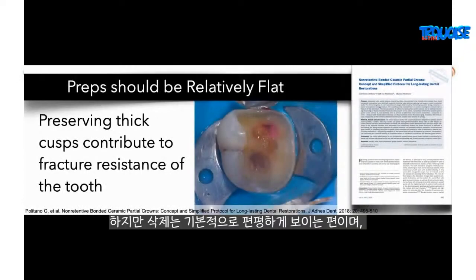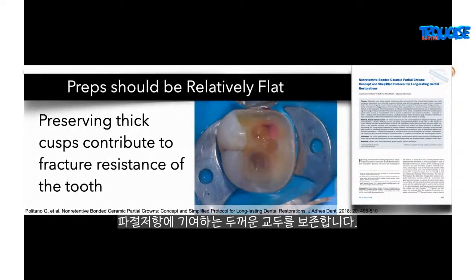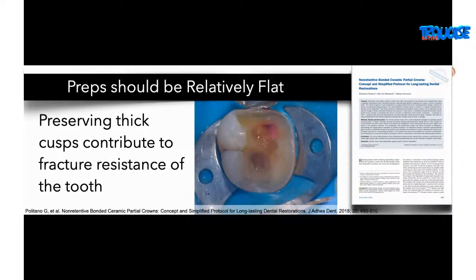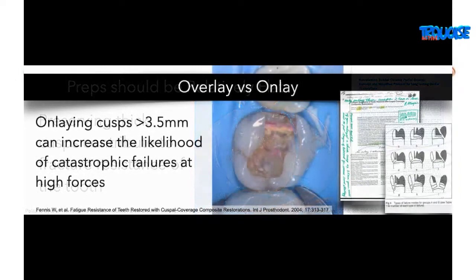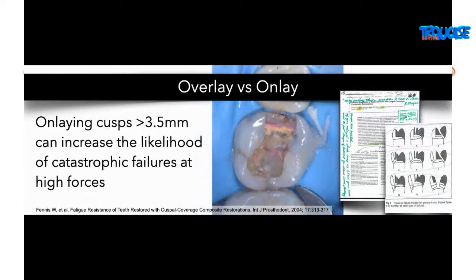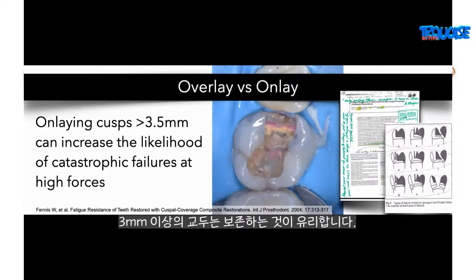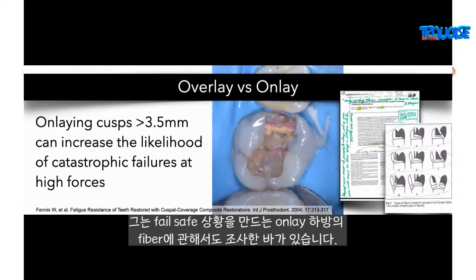But basically the preps look relatively flat, and preserving thick cusps contributes to the fracture resistance of the tooth. By onlaying cusps that are greater than 3.5 millimeters, that can increase the likelihood of a catastrophic failure. So it's better to preserve cusps that are greater than 3 millimeters. That's based on a paper by Fennis. He's also the one who investigated fiber underneath an onlay to make that a fail-safe situation.